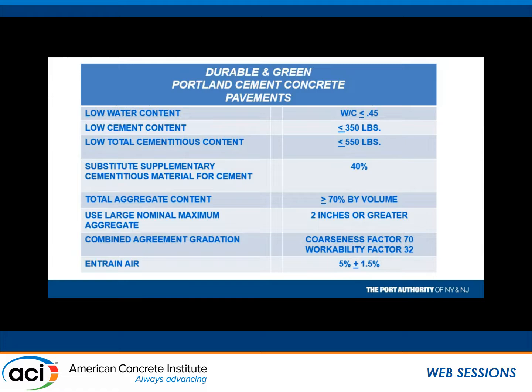And here we go. Substitution for supplementary cementitious material. For bridge decks, we say we want fly ash. For pavements, we want slag, okay, because we get great results with the slag, and because of the control joints, we don't get cracking, okay? So here we mandate slag. Total aggregate content more than 70%, and we want large stone in the mixes. This is always a point of contention with the contractors and the concrete producers. They don't want to do this. So you talk about performance-based specifications. What would we get if we didn't insist on this? Why do we insist on 2-inch stone or better? Because we produce concrete that doesn't have cracks in it.